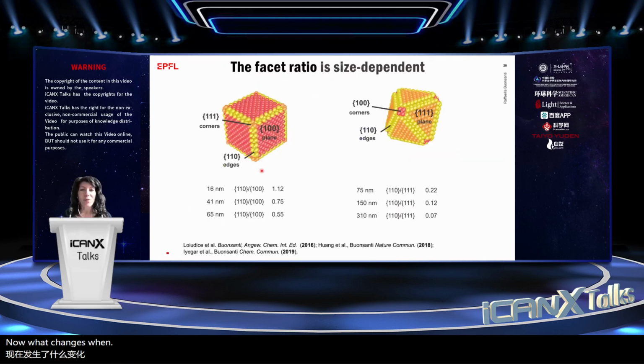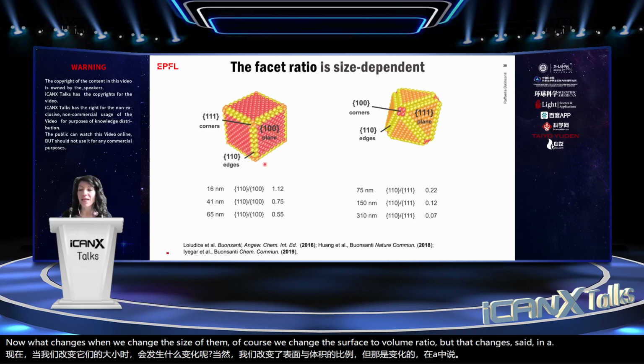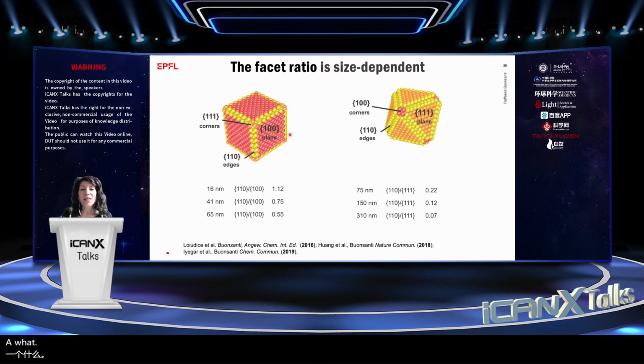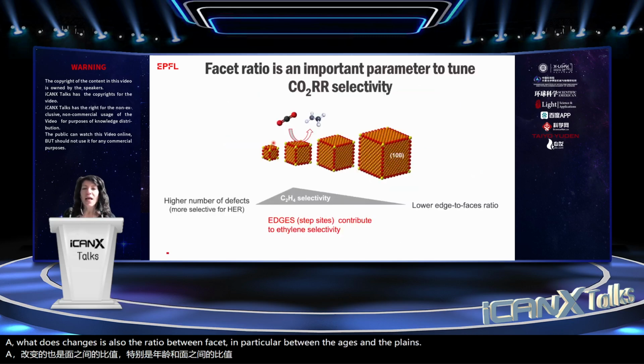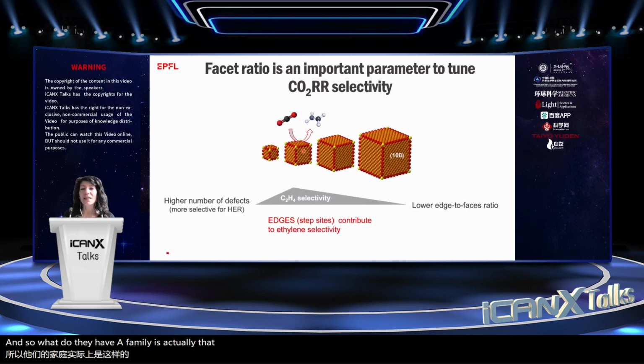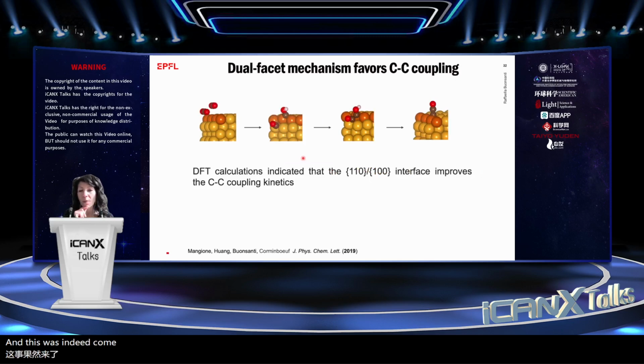Now, what changes when we change the size of the nanocrystals? Of course, we change the surface to volume ratio, but that changes in a linear dependence with the size. What else changes is also the ratio between facets, in particular between the edges and the planes. And so what the data were telling us is that this ratio between the edges and the facets played an important role in the catalytic conversion of CO2, and was contributing to ethylene selectivity. And this was indeed confirmed by some calculations performed by one colleague of mine here at EPFL, which indicated the importance of these edges.